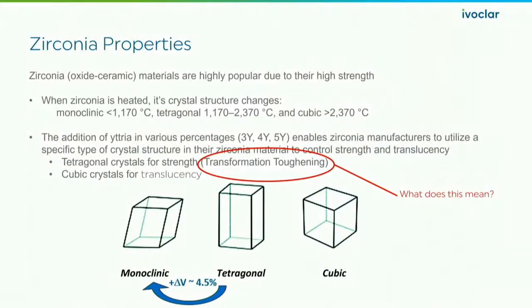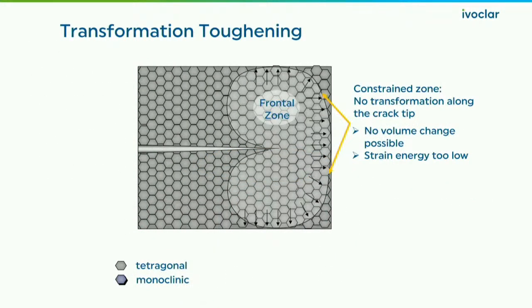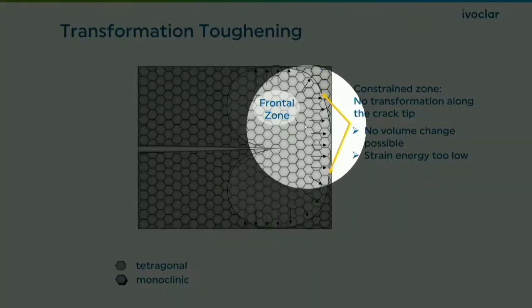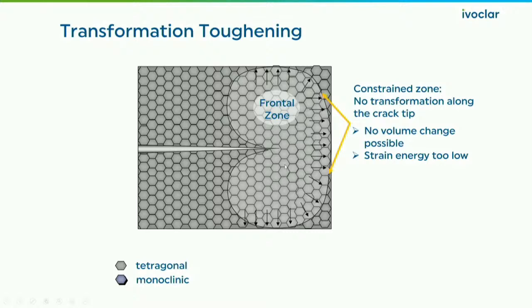Nobody took notes? Okay. So I'll be safe to talk about transformation toughening real quick. There's a volumetric expansion difference between the monoclinic and tetragonal. And when you look at this frontal zone, with all that tetragonal crystalline structure here, what you need to shift to the monoclinic crystalline structure is energy. Whether it's heat energy, force energy, the crack generates energy. And so the more of the tetragonal crystalline you have there, then that energy gets slowed down. When you're in the monoclinic, it tends to be weaker.